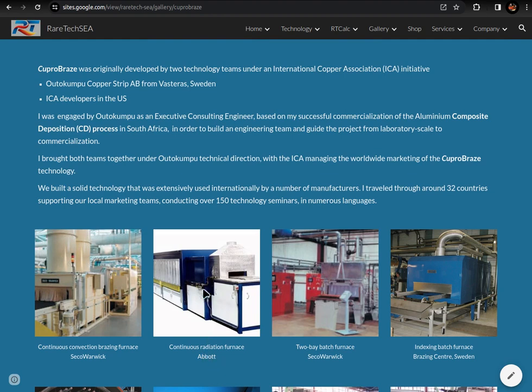And then there's this continuous radiation furnace, which is really similar to what I ended up using in Pittsburgh. And I put a few modifications in it. I got them to add something which made it really tight. And this was made by Abbott. Very nice, simple furnace, and I thought very well priced too. This was a radiation furnace, but it was using gas around to give a radiation effect to do the brazing. But actually nice. You get a nice warm muffle. The muffle's the part that the belt goes through. There's a belt here, and you put the core on there, and off it goes down through the furnace.